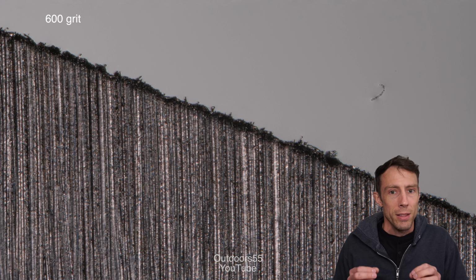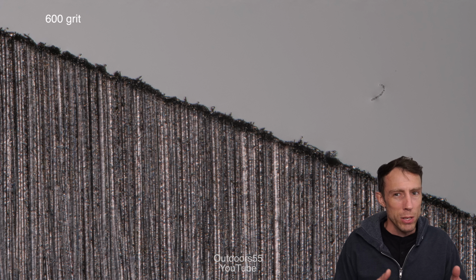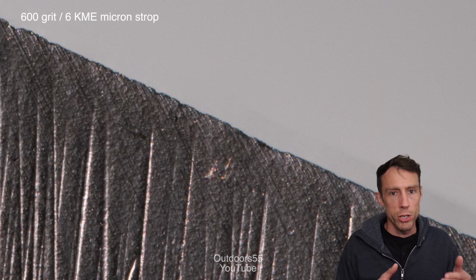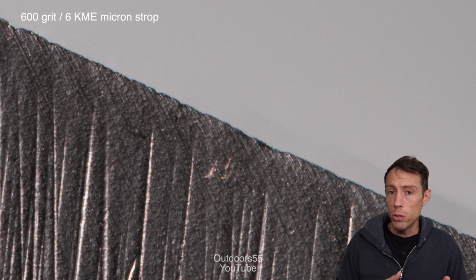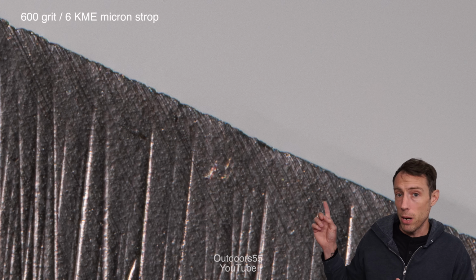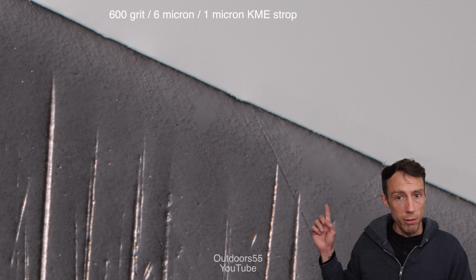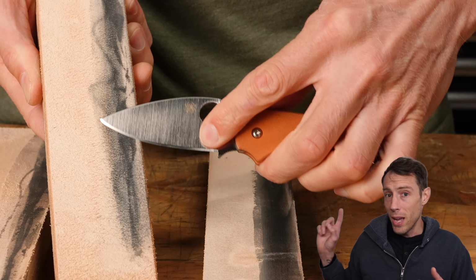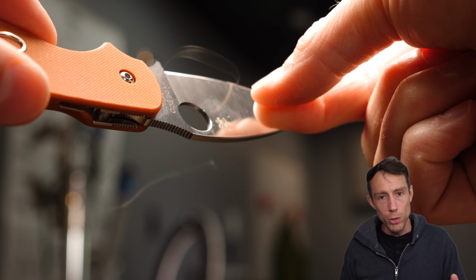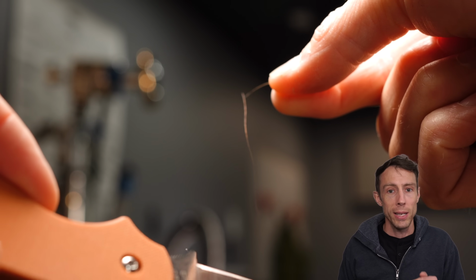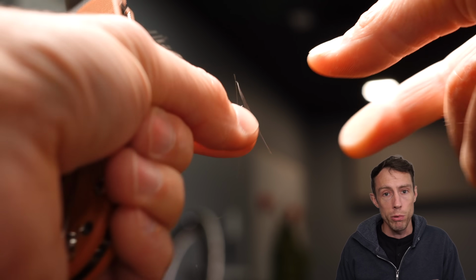smaller burr that takes away less of the apex when it's removed on a 6 micron strop. And we can further refine most of the apex going from 6 micron down to 1 micron. And then finally down to 1/10 micron will give you absolute, and I'm telling you, absolute hair whittling edges pretty much every time, no problem.